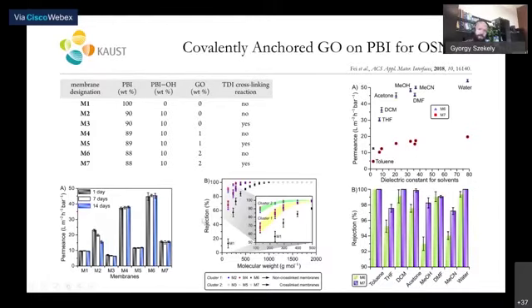If you look at the graph in the middle, you can see that the rejection profiles actually form different clusters depending on what type of membrane you're using. So this is the benchmark membrane at the bottom. And then you can see cluster number 1 in yellow, which is the non-crosslink membranes, which are a little bit tighter than the benchmark membrane. But if you do the cross-linking with the isocyanate, then you get this cluster, the green one, which shows that this is a much tighter membrane. So again, you can fine-tune the performance of the membrane, and you can achieve really tight membranes.